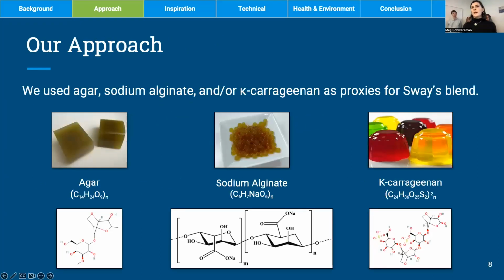So because Sway's formula for their polymailer is proprietary, they have suggested that we look at these three hydrocolloids to use as proxies because they are also sourced from seaweed. One thing to note about their structure is that they have a lot of hydroxyl groups, which means that they're pretty hydrophilic. And this is why Sway is having so many issues with their water barrier performance. And this is the issue that we are trying to fix.